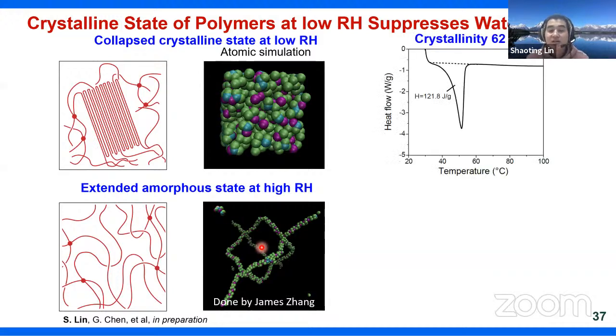So here's our argument. What we argue is that the polymer chains are not in a highly extended, amorphous state. Actually, they are in a highly collapsed state at room temperature at a low humidity level. For example, we use atomic simulation to simulate the structure change of the PEG hydrogel from a collapsed crystal state to this extended amorphous state. And I also use the DSC calculation to characterize the crystallinity, which can reach up to 62% by weight ratio.